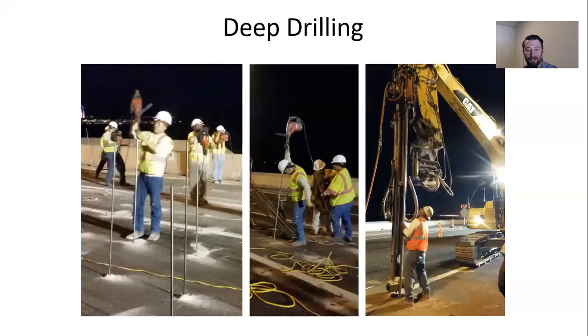But what we were finding is that even with single-digit blow counts in some cases, so really loose soil that we were driving into, that half-inch tubing was building so much skin friction as you drove it deeper and deeper into the ground that it was too much for a full-grown man to lean on a drill and actually advance it to the depths that we were looking for. In this project, closer towards the bridge, we were trying to densify soils at 30 feet. So our longest injection pipe was actually advanced to 25 feet. And again, with that skin friction, we weren't able to advance those pipes to the full depth that we needed to reach to densify that problematic soil at 30 feet.